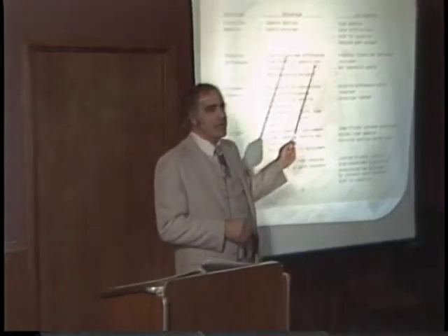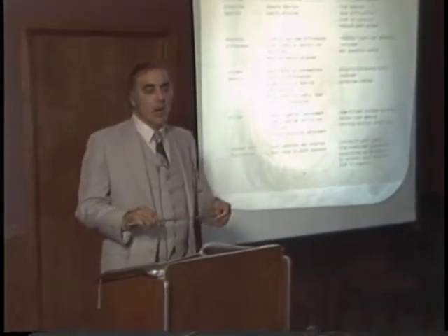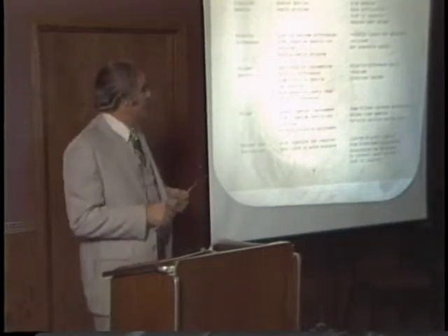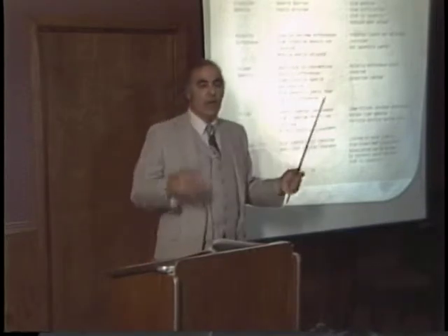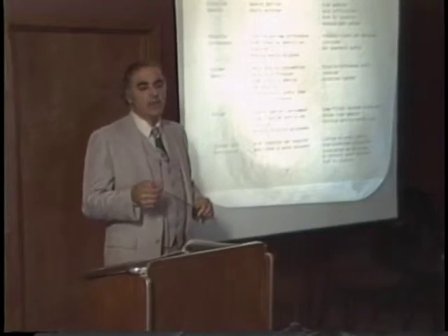And generally, because the peel values in a system are related to the elongation modulus characteristics of the liner, we generally see low peel values. Going after polarity differences, it's good when you have an extreme system where you can use a nonpolar liner and a migrant that is highly polar.